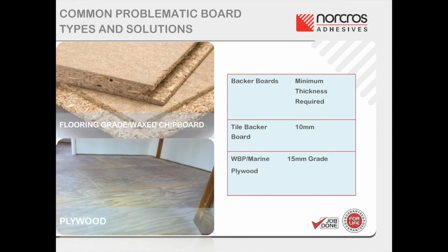Due to the nature of plywood, if it comes into contact with moisture, then it may become distorted, which in turn causes tiles to crack and debond. The solution to this is to ensure the ingress of moisture into plywood does not occur. Sealing with a neat styrene butadiene rubber primer on the back, face and edges of the board is essential to prevent the subsequent distortion of the boards due to atmospheric humidity.